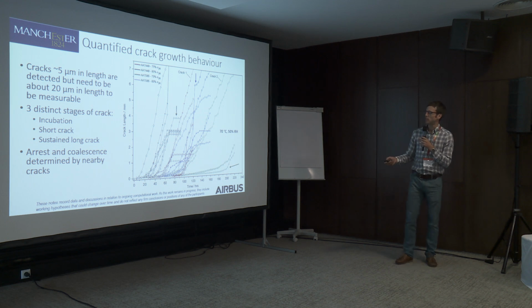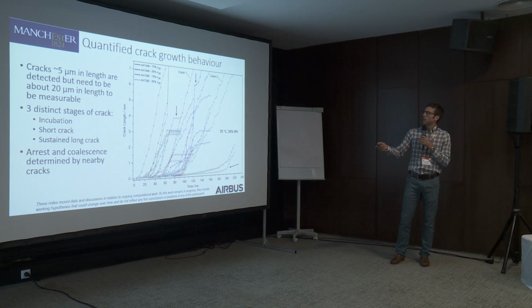And this is the data that we get out, where you can see the crack length as a function of time, and we've tested 7449 and 7085 under 2 different loading conditions. It's worth noting that 75% of yield strength for 7449 is the same absolute stress level as 85% of 7085. And we can see that we get this general behaviour where we have some time taken to form a crack in the first place, so an incubation period.